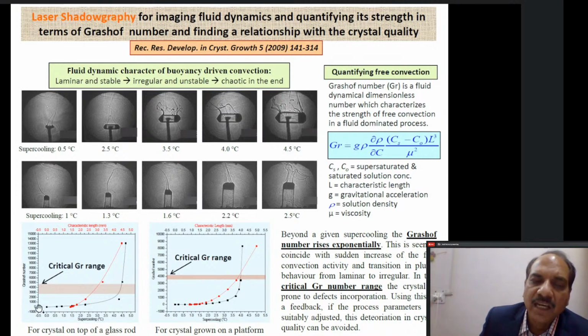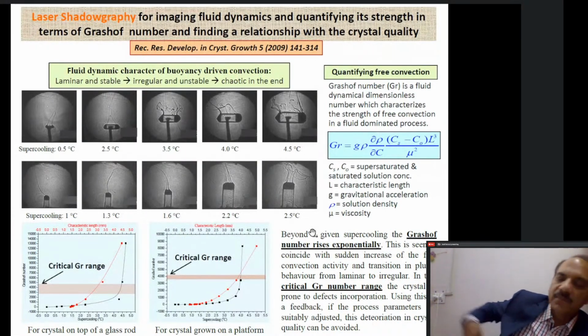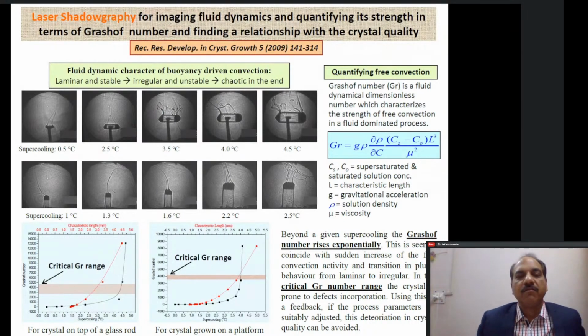We were seeing that suddenly there is a jump in the Grashof number, and this range of Grashof number, which we say is the critical Grashof number, beyond this Grashof number, we were always seeing that the plume behavior is chaotic and the crystal is picking up inclusions. So this was something which we concluded, and we were able to show that there is a relationship between the cooling rates and the crystal quality and the plume behavior which we were able to record. Right. So this is how we found out.